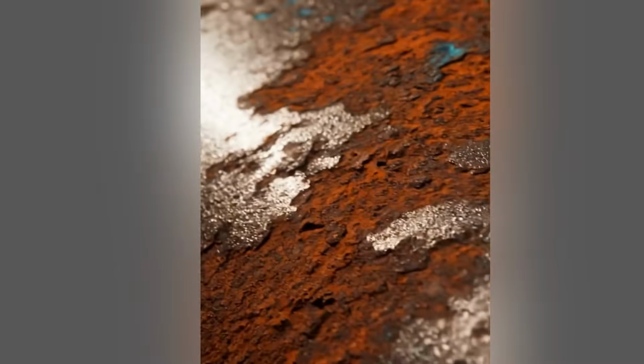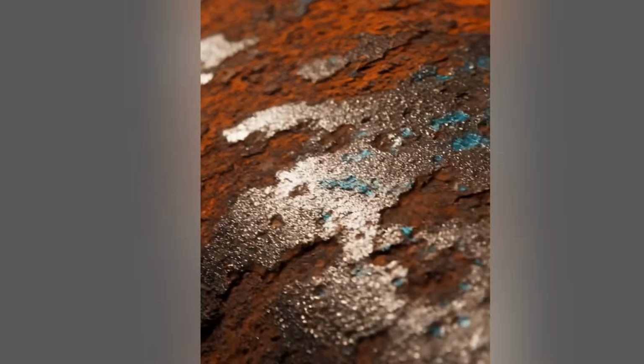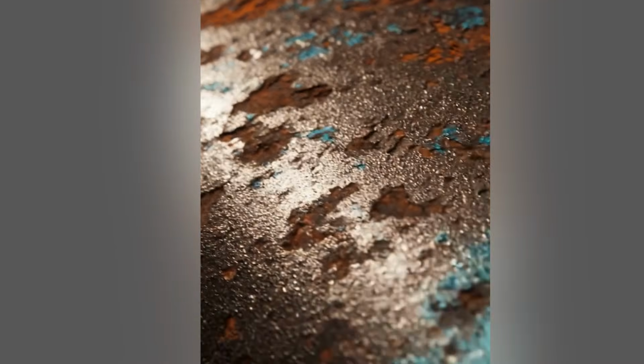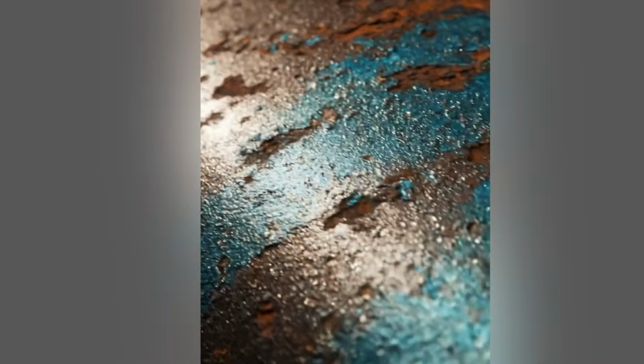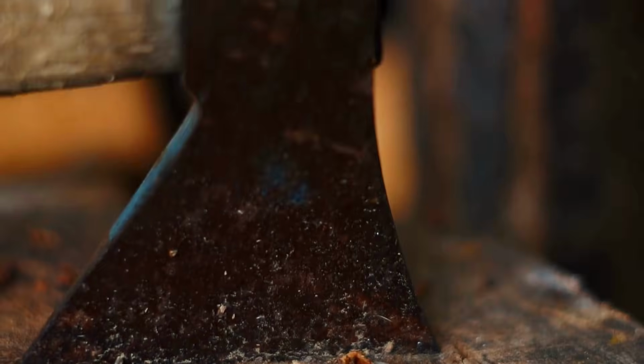When rust attacked Chinese iron, it encountered these slag barriers. The glass fibers deflected corrosion, forcing it to spread sideways rather than penetrating deeply. The result was an axe head that developed protective patina and stopped corroding instead of disintegrating into orange powder.